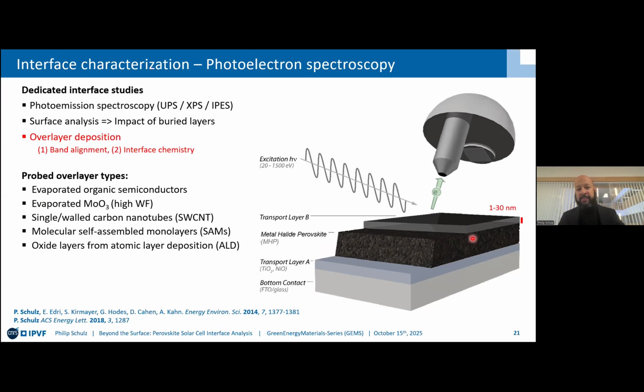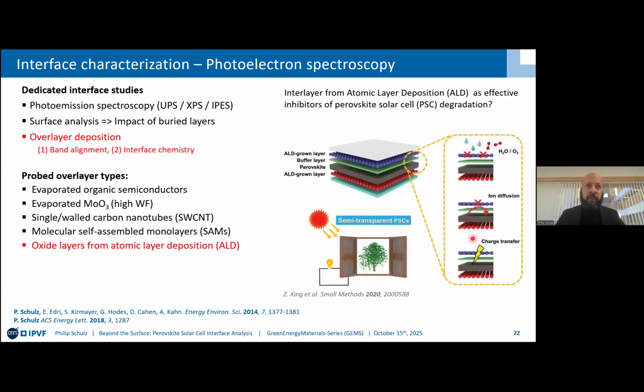In the past, we've exercised this for a host of different materials. This time around, I'd like to focus on the oxide layer by atomic layer deposition. And atomic layer deposition, not just because it can make beautiful oxide films that are ideally completely closed and conformal, but also because in our production technology, ALD plays a more and more significant role, be it also derivatives like spatial ALD. And there we know that ALD oxide films can be inhibitors of oxygen and moisture ingress. They stop ion diffusion, and if you do it right, they still function as good charge transfer layers.